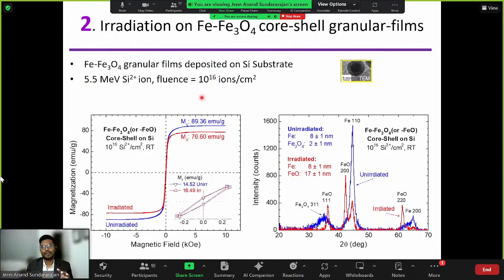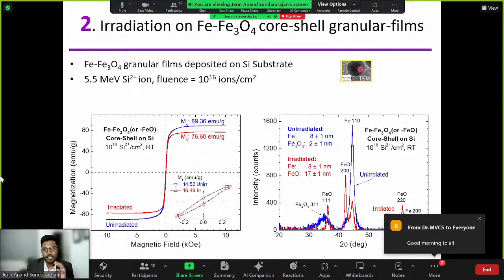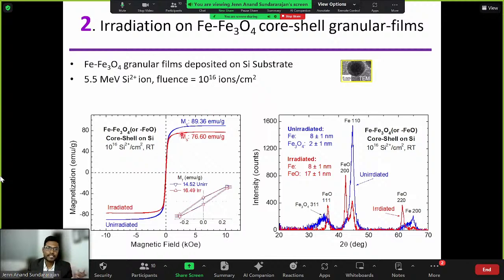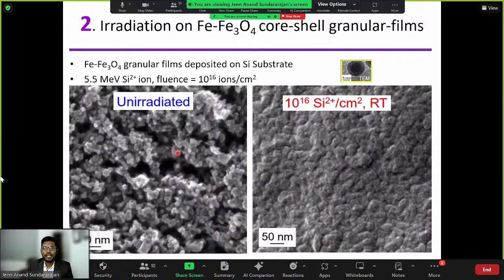The next particle that I'm going to talk about is the core shell, because it has an iron core and an oxide shell. Hold that thought on the outside, and let's see what happens here. Here you can see, because of the iron core, it stayed ferromagnetic, and after the radiation also, it stayed ferromagnetic, so no big change. Even the grain size has not grown much, only the oxide shell grain size has grown a little bit more, from 2 nanometer to 17 nanometer. So the core is retained and preserved even with the high dose of radiation, as you can notice. The irradiated film looks like a uniform film, and you can still see the core particles. The core is retained.